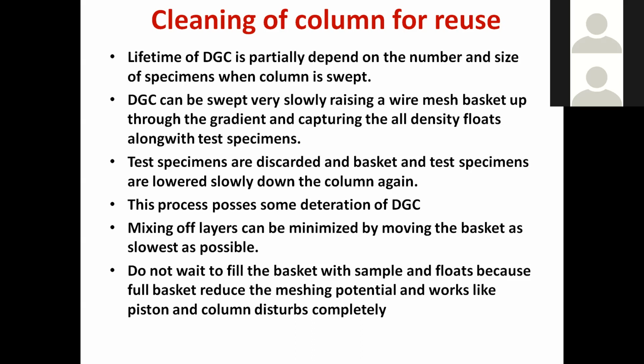So how much time is required to bring it up? That should be around 5 to 6 hours, 5 to 6 hours to lift that basket from bottom to top. So how is it possible? A motor arrangement and a gearing arrangement are there to slow down its speed. A current controller device is also there. So you adjust the time, how much time you set to bring it up and to bring it down.